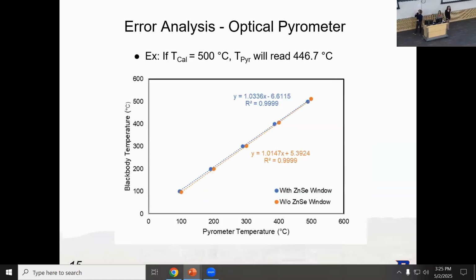So what we can see is there is a very significant difference in the sample temperature and the recorded sample temperature. For our black body calibrator, if the true temperature is set to 500 degrees Celsius, we will really only be recording around 447 degrees Celsius. So we did need to take this into account. And with this high R squared value, we were able to interpolate this to the higher temperatures that we recorded at.